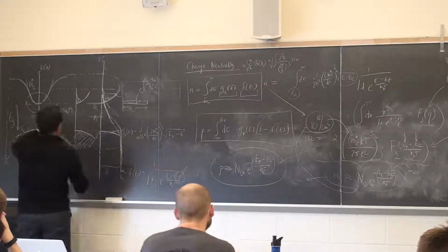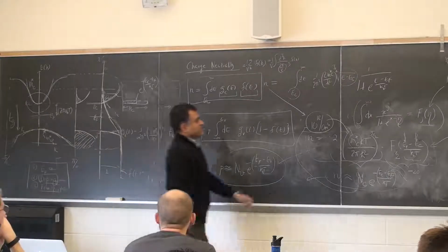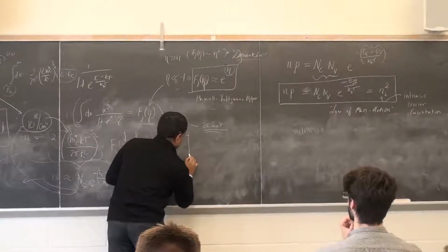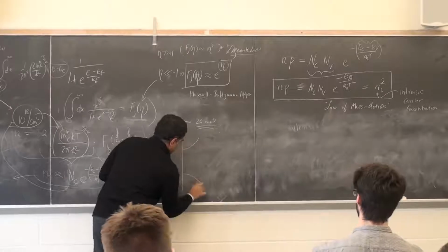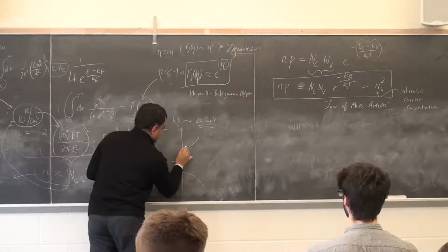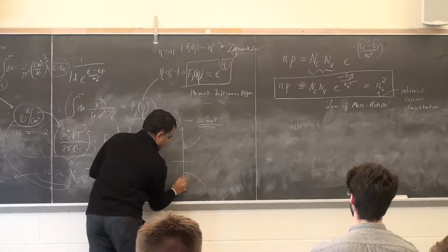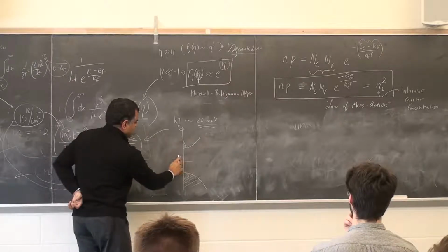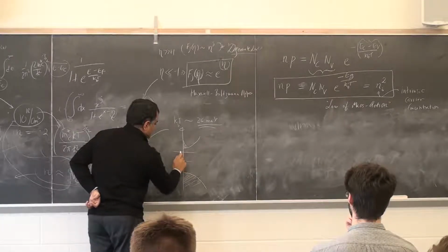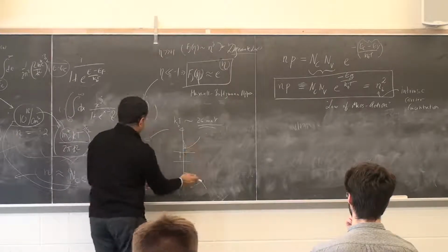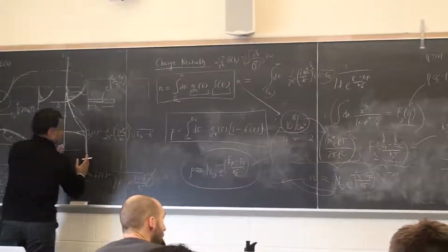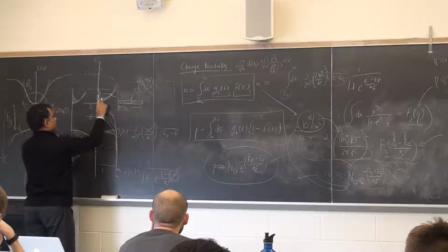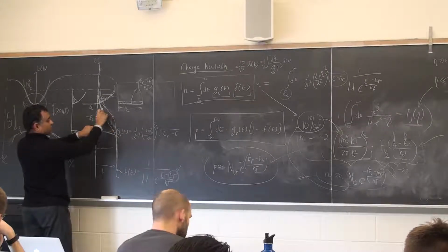But here's what we're doing. Let me sketch this picture one more time. I have my conduction band DOS, valence band DOS, right? And let's say my Fermi level is in the middle, then we just talked about the Fermi electrons will be like that, and there'll be holes like that, which will be filled, right? Now, if I move the Fermi level up by this much, I moved the entire Fermi Dirac distribution rigidly up. So as a result, this function moved like that. Does that make sense? It just moved up by that voltage, all of these points.